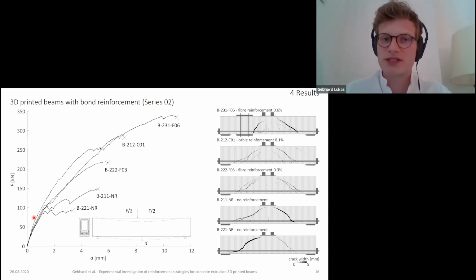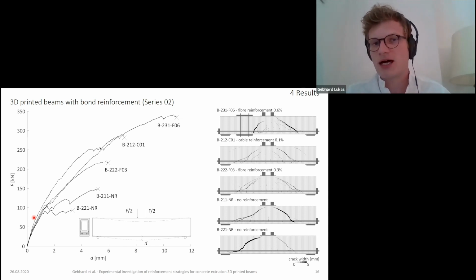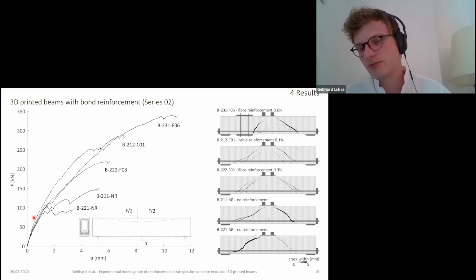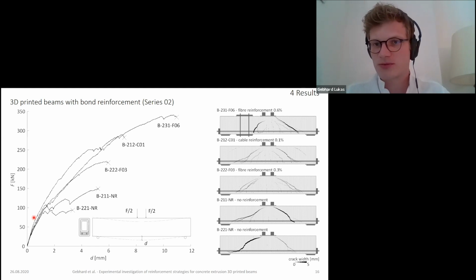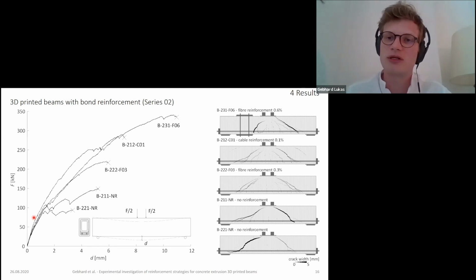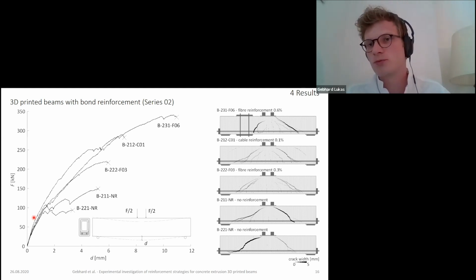And then the cable reinforcement with only 0.1% was able to increase the force even more than the 0.3% of fibers. But there were fewer diagonal cracks and the cracks were slightly more open. And on top, we see the beam with the highest ultimate load, so with 0.6% of fibers. Here it needs to be mentioned that only the right side of the beam was fiber reinforced. That's why we had external shear reinforcement on the left side to provoke the failure on the right where we had the fibers. And also we could not double the ultimate load for double the fiber amount.